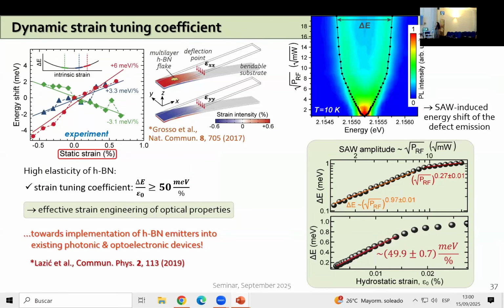Our results show that the energy shift of the defect emission, shown here again, is around 50 millielectron volts per percentage of strain. This is an order of magnitude higher than previously obtained results by other authors, who observed in multi-layer hexagonal boron nitride flakes coefficients of, let's say, a maximum of 6 millielectron volts per percentage of strain when they applied static strain to the HBN flake.